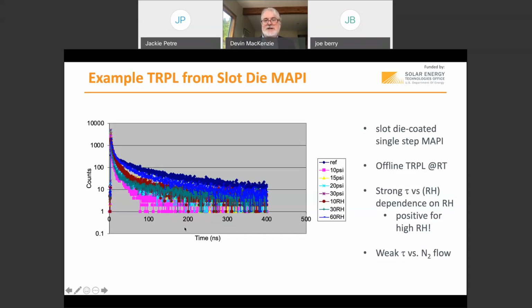It's also interesting to remember that time-resolved photoluminescence gives, of course, the minority carrier lifetimes, the basic photophysics, but it's not the only story for making a device. So we can have high lifetime, but not something that makes a very good device. We'll talk a little bit about that in a moment. It makes sense, the fact that we're getting longer lifetimes the more we crank up the humidity, is the antithesis of where everyone wants to go in devices, and everyone is seeing the best devices at low humidity. Ultimately, spoiler alert, it's about grain size. We can make huge grains at high humidity, and those really big grains can give quite good TRPL signal, but they can make lousy devices.